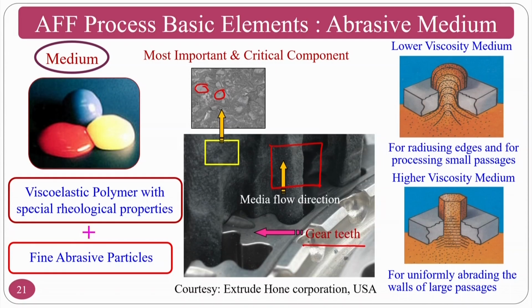Normally, there are high viscous medium, medium viscous medium as well as low viscous medium. So, two examples that we are seeing here are called low viscous medium and high viscous medium. So, if I want to abrade uniformly, then people have to go for the high viscous medium. In a high viscous medium, whenever you are applying the extrusion pressure from one direction, this medium is so high viscous that it will extrude through the hole. For example, a hole that is drilled by EDM process or laser beam machining process or any other process. You are just putting some pressure, this pressure extrudes the medium across the surface to be finished and it comes out as a straight medium slug.